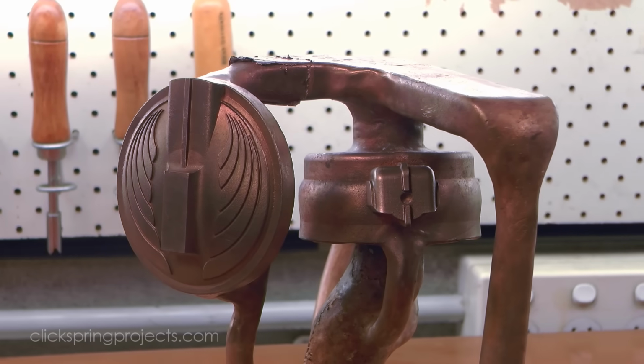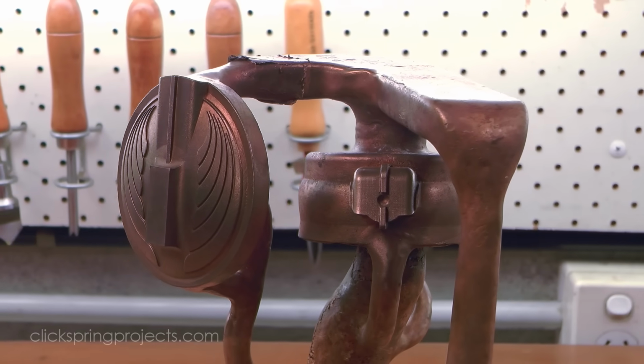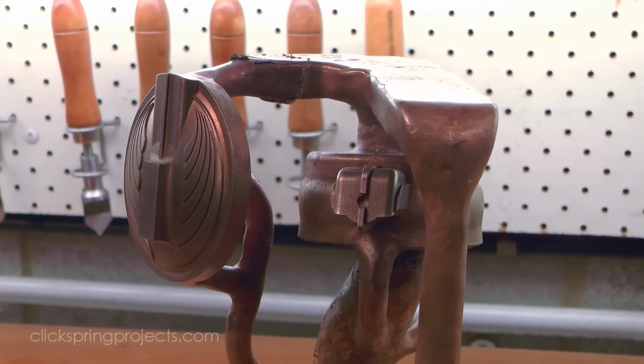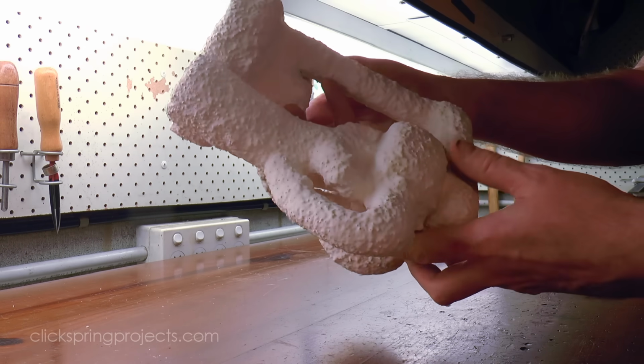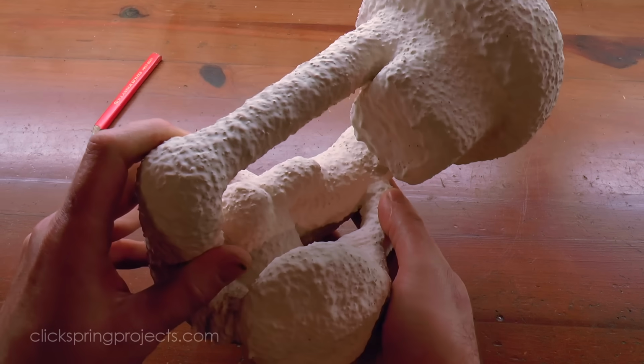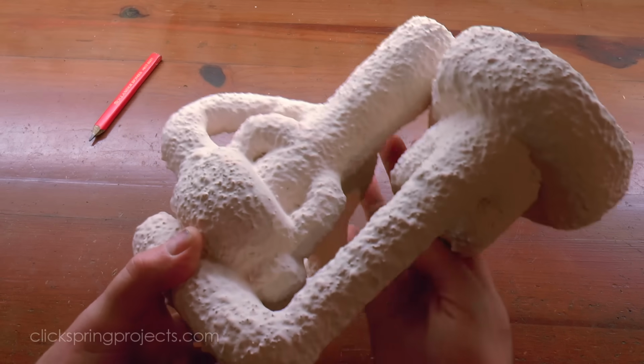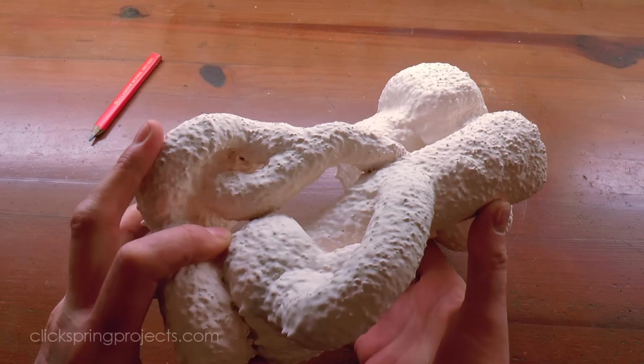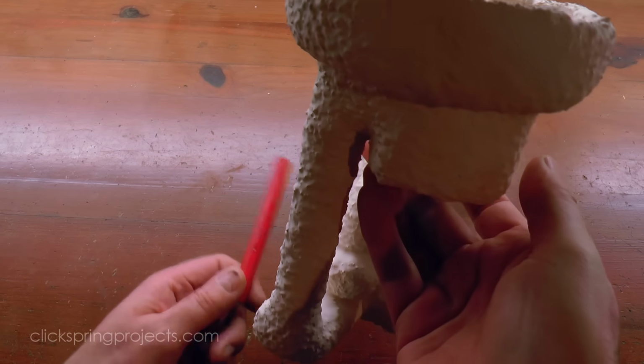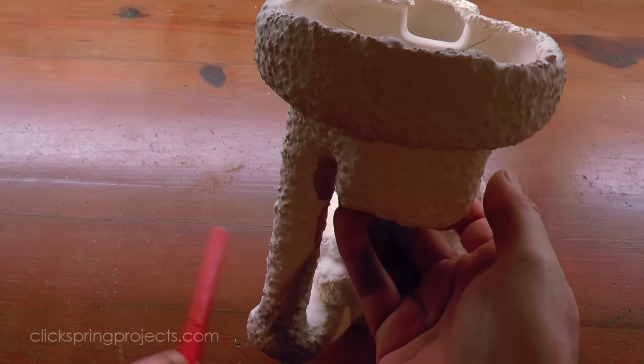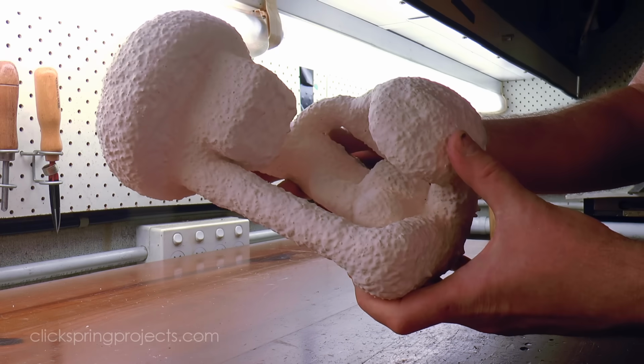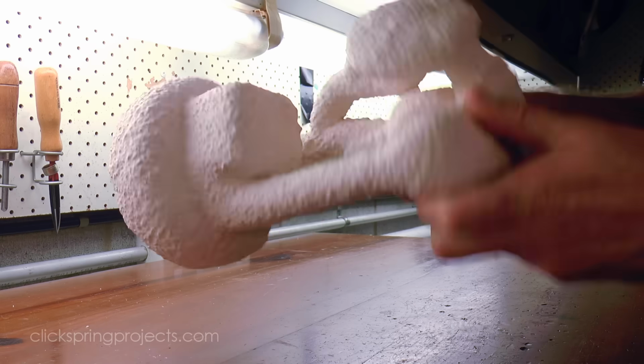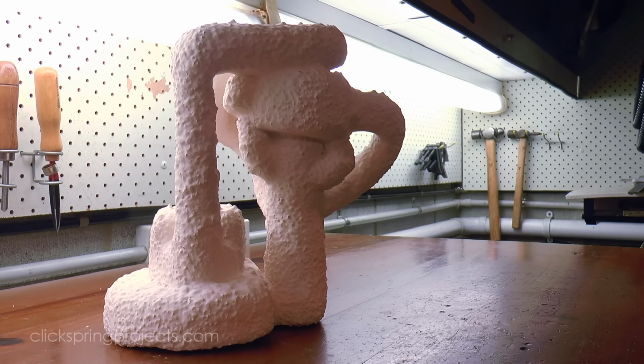In this process, the wax model is coated in multiple layers of ceramic slurry and refractory material, de-waxed and then fired to provide a high quality vitrified mould for metal casting. It's not by any means a simple or fast activity, with many steps to the sequence. And like most foundry work, not for the faint-hearted. There are a lot of hazards and variables to control for a good outcome. But with care, using ceramic shell as the investment can deliver superb results.